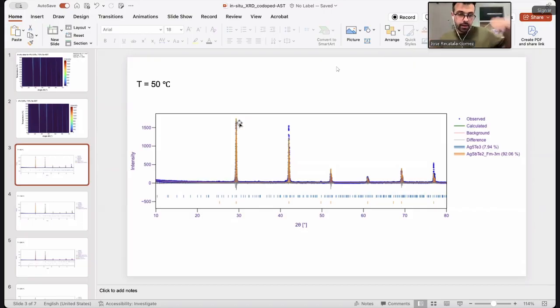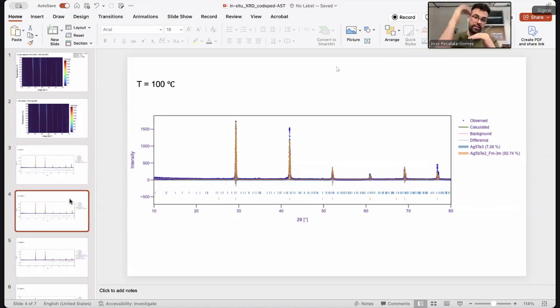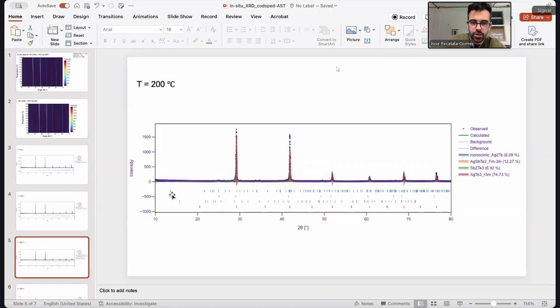But basically, the phase diagram is very complex, and non-equilibrium synthesis has a very big impact on it. Non-equilibrium synthesis even more. And I'm glad that you raised that point, because as you raise the temperature, what happens is that you start seeing the decomposition of the silver antimony telluride. Most surprisingly, it decomposes into antimony telluride first. And I know that because the phase fraction of antimony telluride increases with temperature, right?